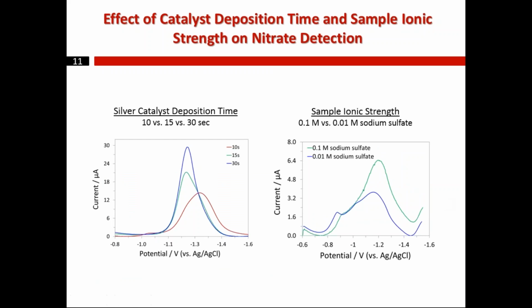The next thing that has to be optimized was the amount of silver that was deposited onto the electrode. As you can see over here in this image, we observed that by increasing the time that we were depositing silver onto the electrode, we could get a sharper peak for reduction of nitrate in the same concentration. However, going beyond 30 seconds for deposition of silver was not practical since silver was tending to come off the surface of the electrode when it was deposited for longer times.